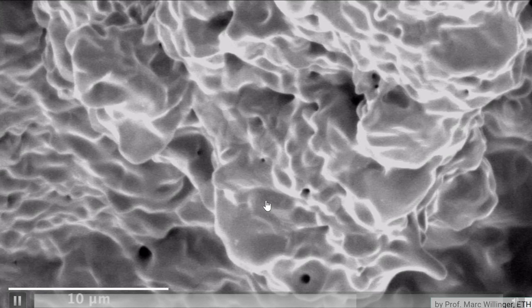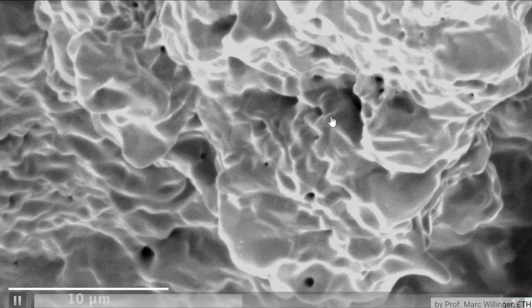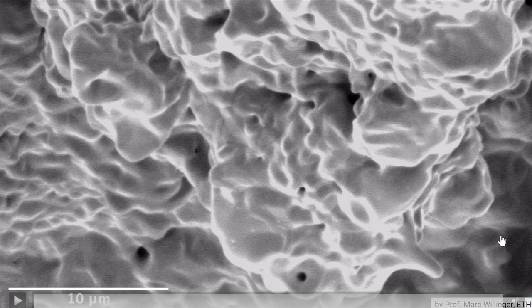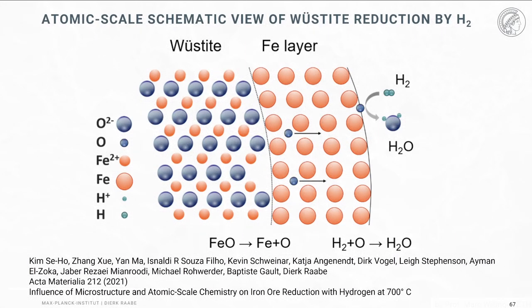Here's a very nice environmental microscopy observation from our colleague Professor Marc Willinger from ETH Zurich. And you can see here that a film of iron is formed on the oxide. Below is the coarser oxide, and on top of that, when you expose it to hydrogen here in the electron microscope, you see how this iron film forms. That also means that further hydrogen or oxygen transport in the other direction must go through this iron layer.